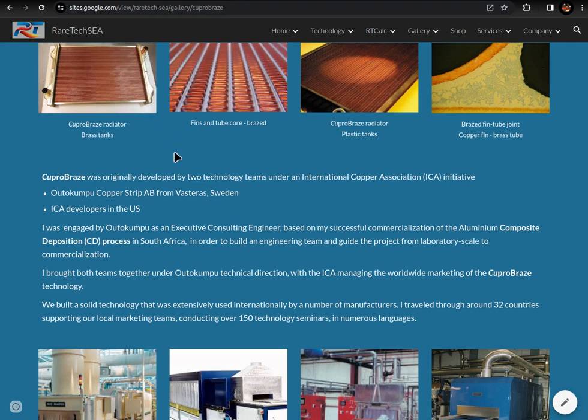What happens with brass? Because of the zinc in the brass, it tends to what we call de-wet. In other words, the braze alloy will start to wet, go in the joint, and then it'll jump out. And then you will basically have huge problems on the tube to header. They don't seal. So we had to develop techniques on how we would actually get the tube to headers to seal. There was quite an art form to that. It's not as simple as most people think. It's actually not as simple as aluminium.